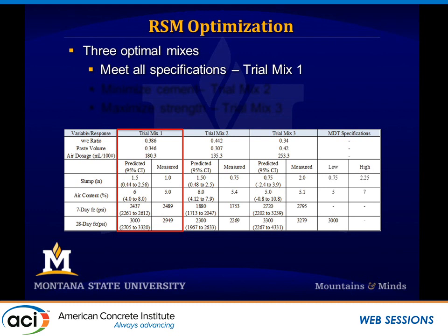So we said, all right, well, we don't want to cancel out the benefit by having to add a bunch more cement to this mixture. So we said, all right, let's minimize the cement. And the way that we did that is said, let's just drop off that strength. And by minimizing the cement, what you would expect to happen is the paste volume should go down, right? Because that's where the cement is in the paste. So the paste volume went down, and then to make it workable, the water-cement ratio had to go up. Right? If you remove the flowable part of concrete, then you have to add in some more flowable stuff, and so you add more water to the mix. And so this is what the response surface methodology gave us, and it passes my test and what it should have given us, okay?